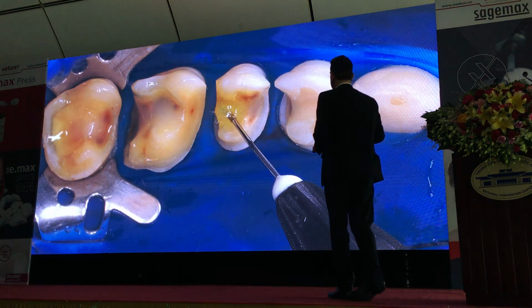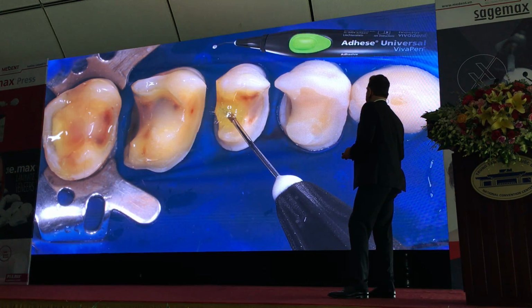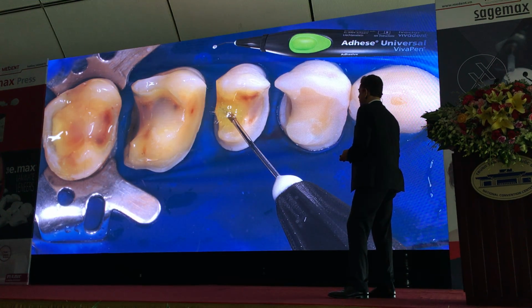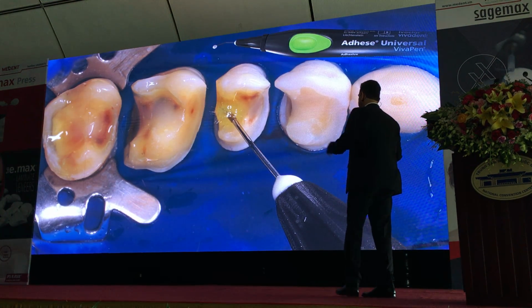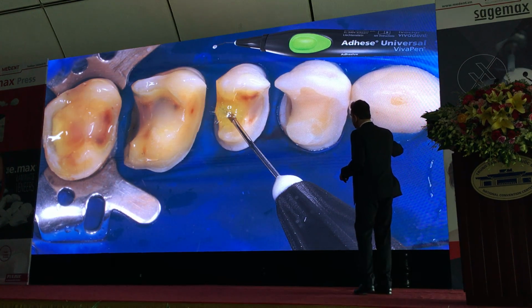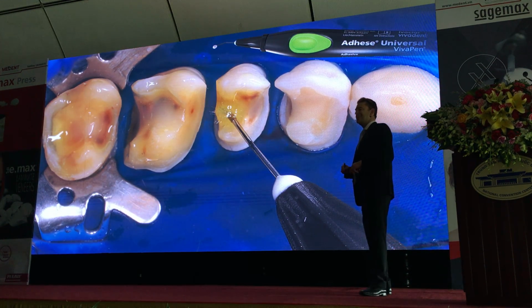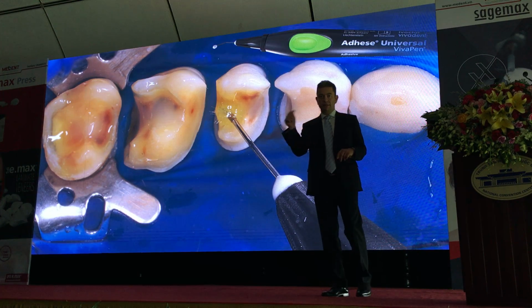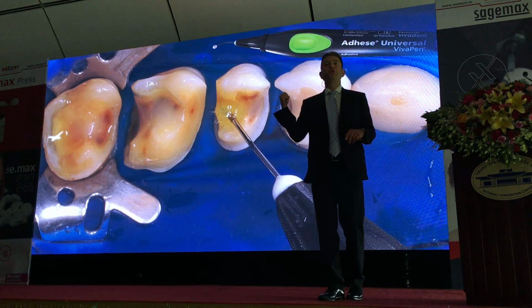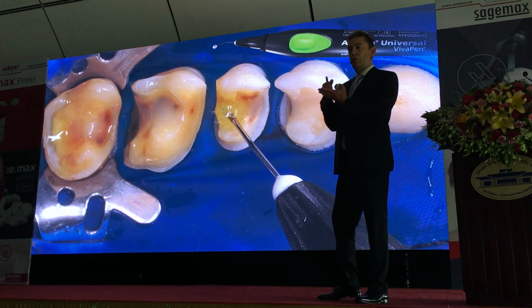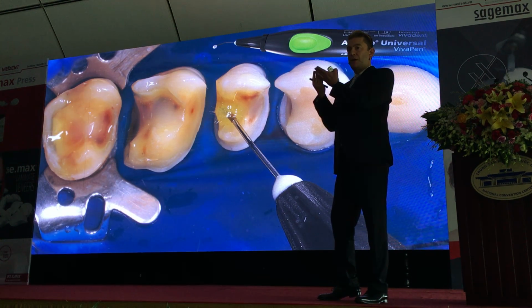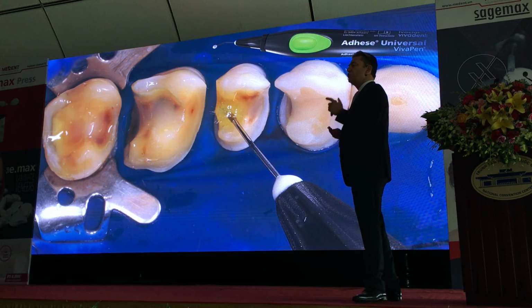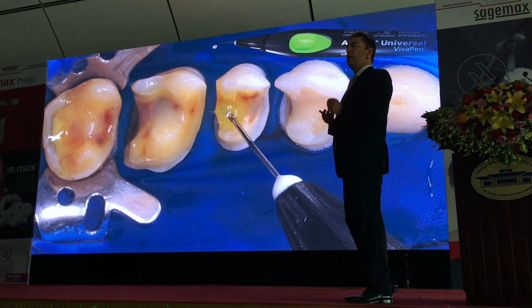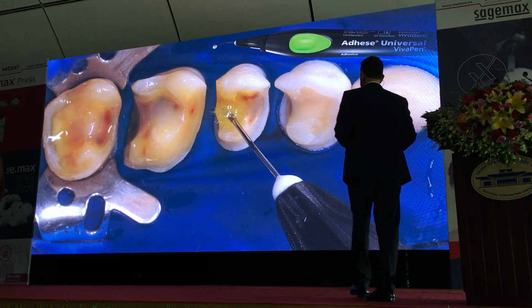And then we are using a bonding agent. In this case, my preferred bonding agent is Adhese Universal or Tetric N-Bond Universal. So we scrub that in for at least 20 seconds. Scrub it in. And then we need to blow it out. We need to blow the solvent out of this bonding agent. Yeah? And then we need to light cure it before we cement the restorations.